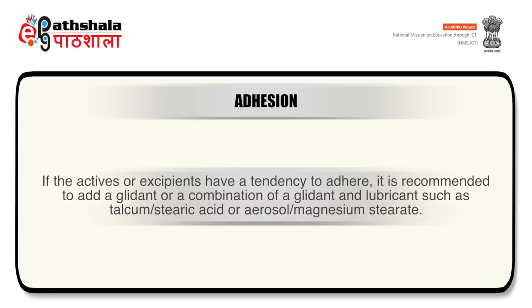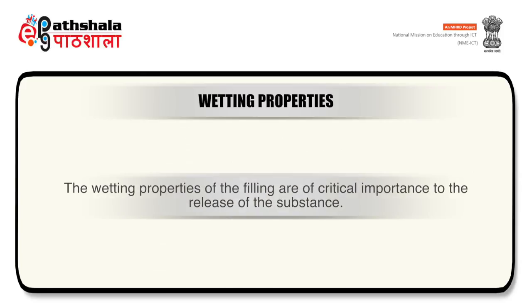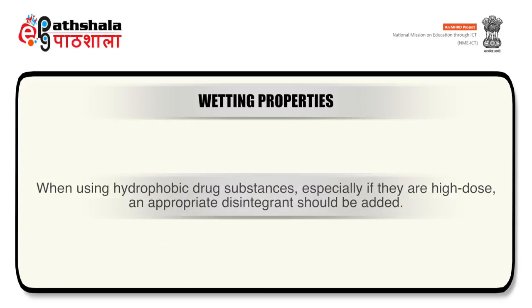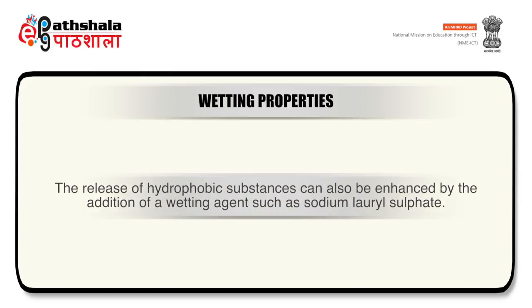Regarding adhesion: the tendency of many drugs or excipients to adhere leads to difficulties during capsule filling. It is recommended to add a glidant or a combination of glidant and lubricant such as talcum, stearic acid, or aerosil. Regarding wetting properties: when using hydrophobic drug substances, especially at high doses, an appropriate disintegrant should be added. Strong disintegrants include croscarmellose sodium and crospovidone, while moderate disintegrants such as corn starch or sodium starch glycolate may often be sufficient. The release of hydrophobic substances can also be enhanced by addition of wetting agents such as sodium lauryl sulfate.